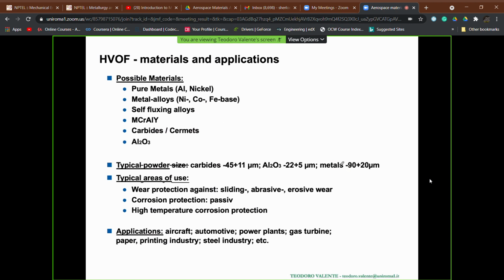Which are the materials which are possible and which are those most used? You see here, I have mentioned alumina, but just as experiments. Typically, the materials have a not very high melting temperature. So pure metals, for example, or metal alloys, or self-fluxing alloys, which are again metal alloys. MCrAlY, which we have discussed because it is the bond coat of the thermal barrier coatings, and cermets, but having as a reinforcing ceramic phase not an oxide but a non-oxide ceramic, typically carbides.